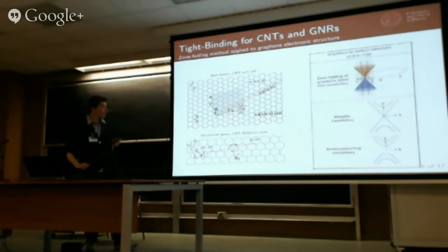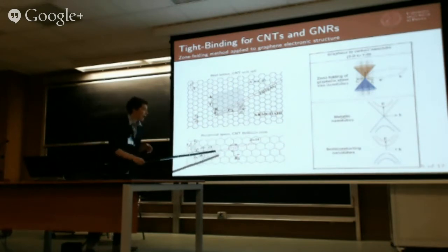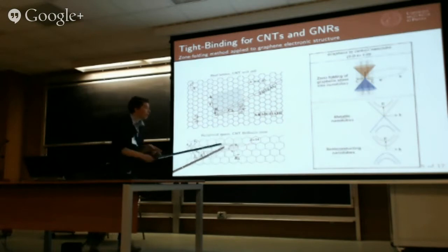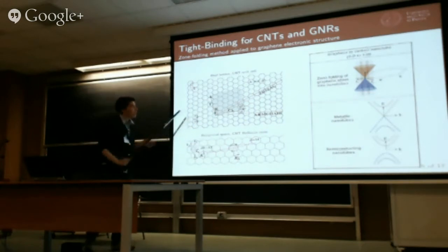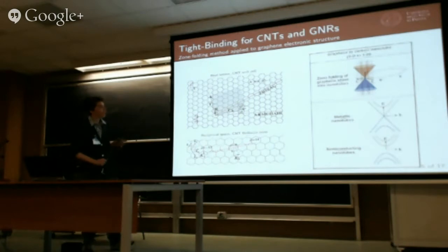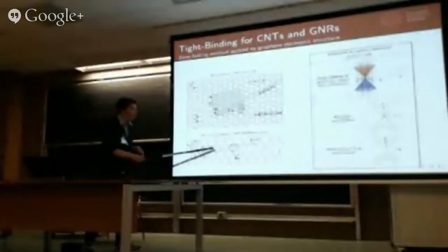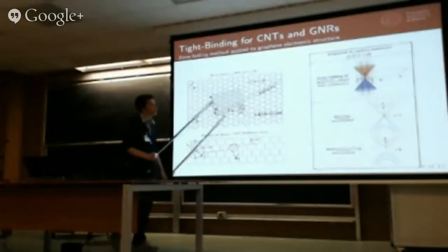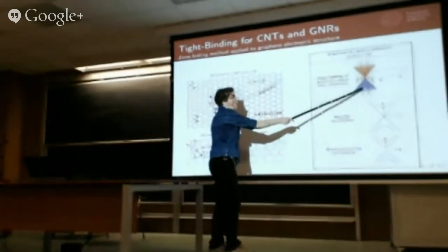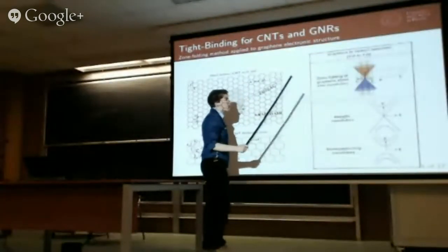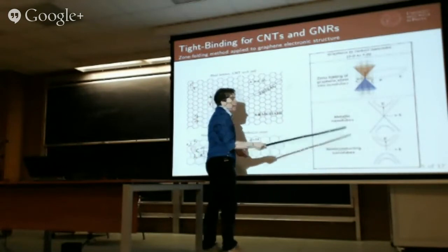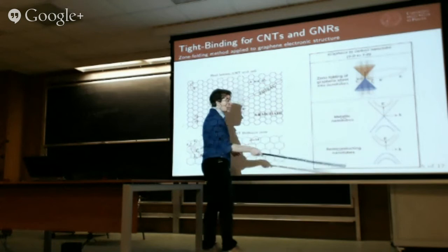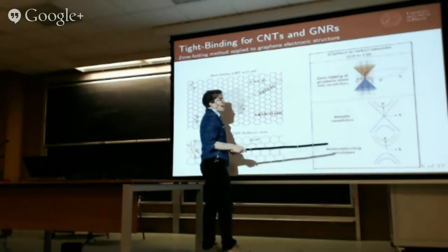Usually one considers the reciprocal space lines, which are shown in red, for the system under investigation, for instance, carbon nanotubes or graphene nanoribbons, which are clearly related to the real space geometry shown in the picture above. We can use these cutting lines to cut the electronic structure of graphene along their directions, and when we consider all the obtained sections, we get the electronic structure of a metallic or a semiconducting system.